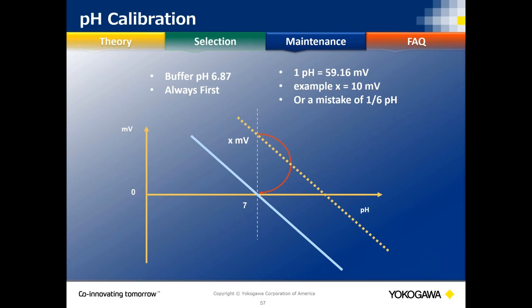So at about 15 to 20 millivolts, you need to clean it again. 35, you're going to start to get sluggish. Analyzers vary. They will alarm at 60 millivolts. They'll alarm at 120 millivolts. You can bring it in if you want. But pretty much if you get to 80, 85 millivolts, you need to look at, if cleaning's not the issue, starting to replace your electrode, okay?